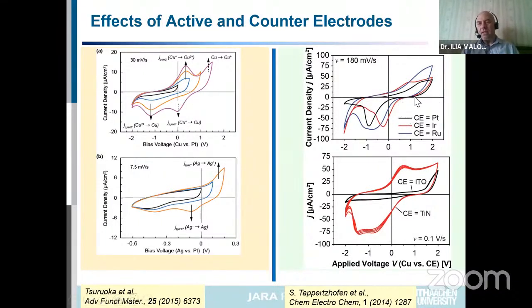And you see that different noble materials, platinum, iridium, and ruthenium, have different catalytic activity. You see how early iridium promotes the current, and platinum, which is also an inert element, starts much later. So this means that you need a much lower voltage or much less energy to apply, and iridium will allow the reaction, whereas platinum will not.